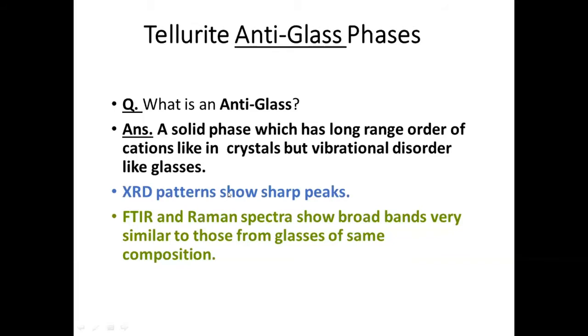Whereas if you do the Raman studies or infrared studies on these materials, because they have a vibrational disorder, the phonons cannot propagate long distances. They show very broad Raman and FTIR bands, which are very similar to those from glasses. Whereas the crystalline materials show sharp peaks in both X-ray diffraction studies as well as in spectroscopic studies like Raman studies.